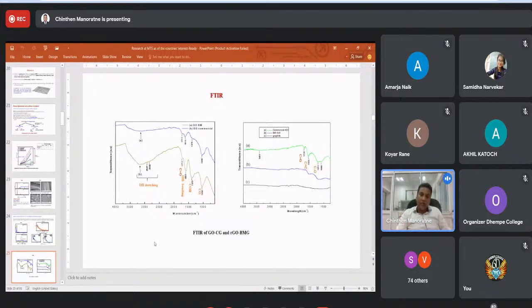And now this shows the FTIR spectra of two products. You can see these functional groups are very high in ball mill graphite because a lot of reaction sites are available and a lot of reaction takes place, making a lot of functional groups. That is because the particle size is reduced and the reaction is very efficient, and that is not available in the larger particle size graphite oxide produced from larger particles.